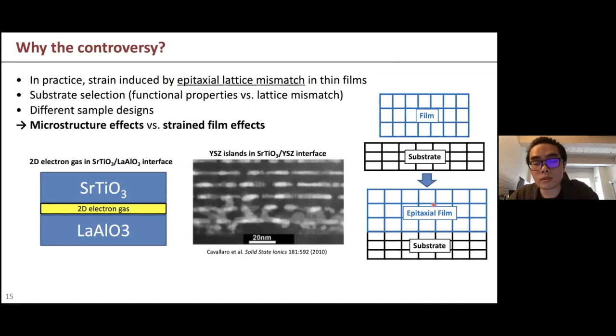In experiment, when we want to apply epitaxial strain to the thin film, we choose a substrate that has a different lattice constant from the thin film. We grow the thin film on it, and then it can either be stretched or compressed. However, the quality of the thin film is very critical in actually creating this kind of strain. And also the thin film cannot be too thick, otherwise the strain will just relax.